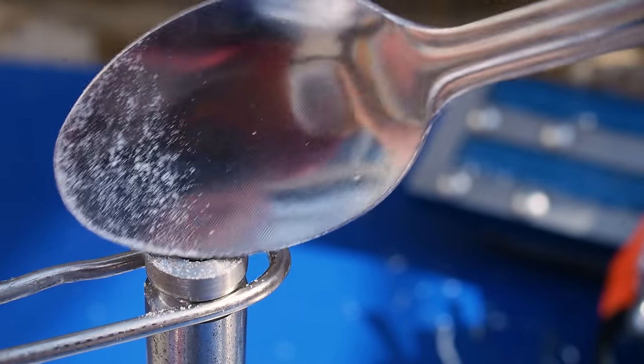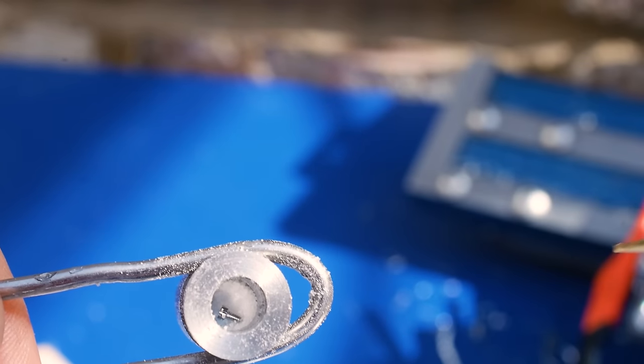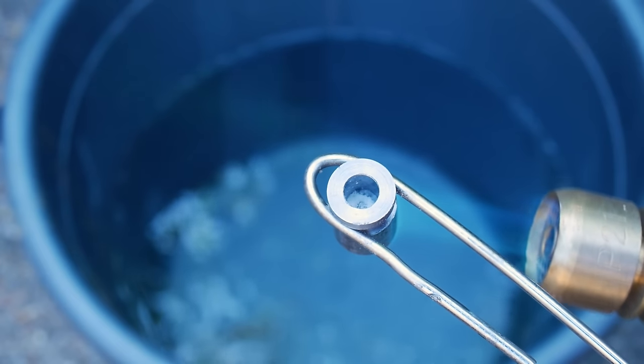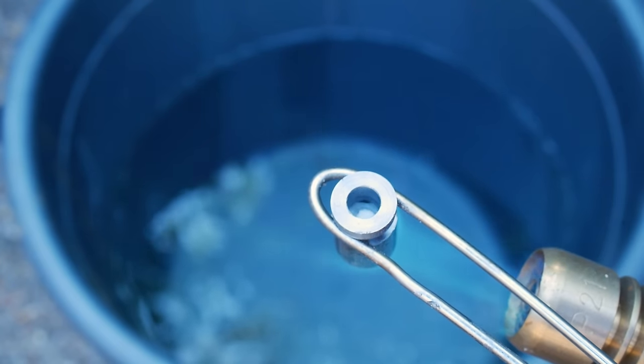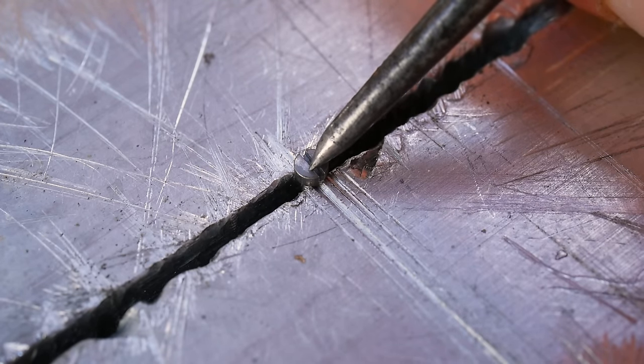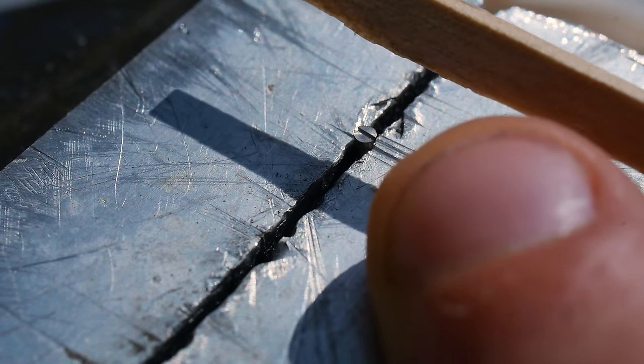To circumvent this, I machine a simple pot, which I fill with boric acid. I put the screw into the boric acid pot and heat the whole assembly. I then quench the pot and screw together in water. I check the screw is hard with the scribe. If it skims over the surface without scratching, I know the heat treatment was successful.